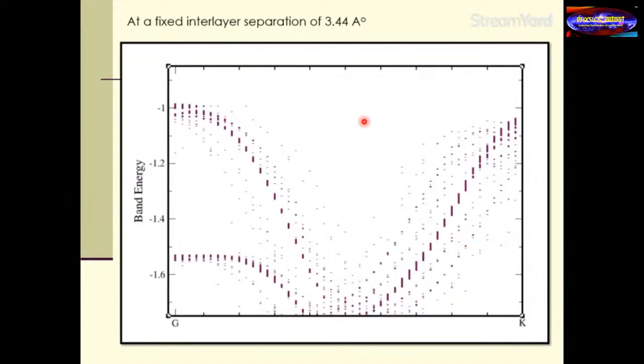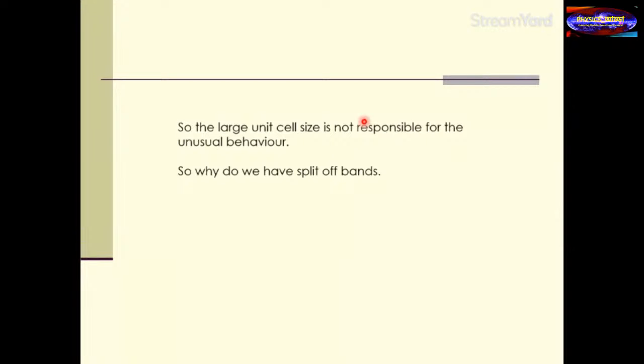One thing before I move on to try to understand what the origin of this could be, what I can immediately say is that it's not because of the large unit cell and the fact that my K space becomes very small, because what you see is I've taken two very similar sized large unit cells. One has it and one doesn't have these split-off bands. So there's something more which is happening over here.